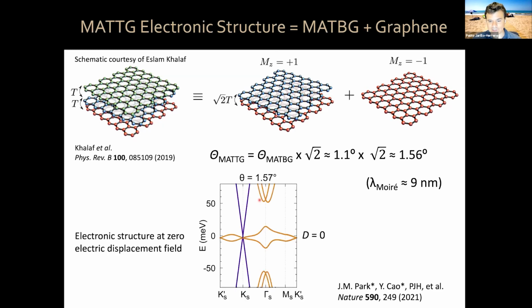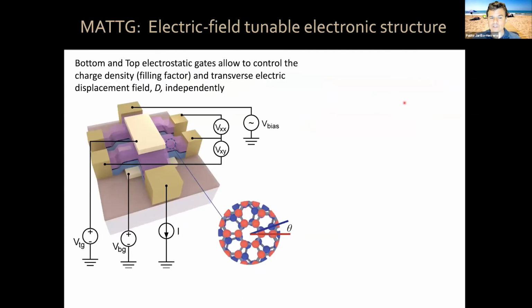Now, this is the electronic structure. When there is this mirror symmetry, both structurally and also electrically, all the 3 layers are at the same potential, or at zero displacement field, then the energy versus momentum gives you these 2 sets of bands. The orange ones are the magic angle flat bands, the flat bands corresponding to the magic angle twisted bilayer graphene-like sector, or block. And this Dirac cone corresponds to the monolayer graphene sector. Now, that was the situation when all 3 layers are at the same potential. In our devices, we have the magic angle twisted trilayer graphene.